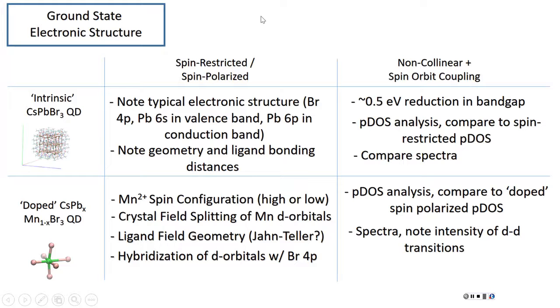And the notable things to mention for both of these systems, just starting with the intrinsic spin restricted calculation, is it follows a typical electronic structure that's been reported in literature, where the valence band is made up primarily of bromide 4p or 5p, I can't remember. It's either 4 or 5p orbitals, but they're p orbitals, and then lead 6s orbitals, and then in the conduction band, the band edge is made up of 6p orbitals. You can see that when you do partial density of states, or PDOS.